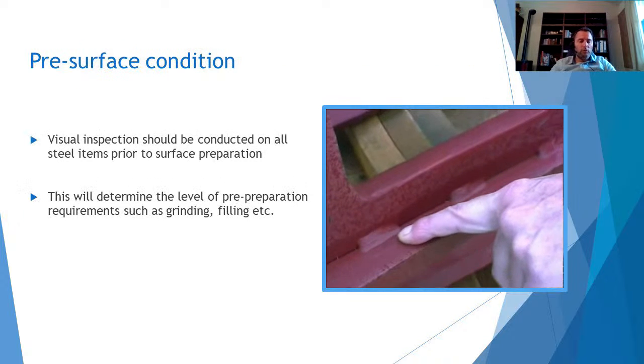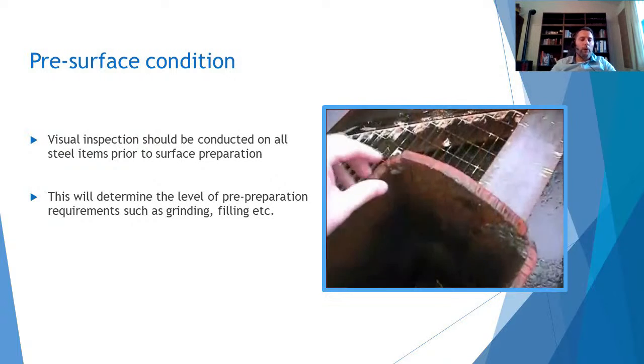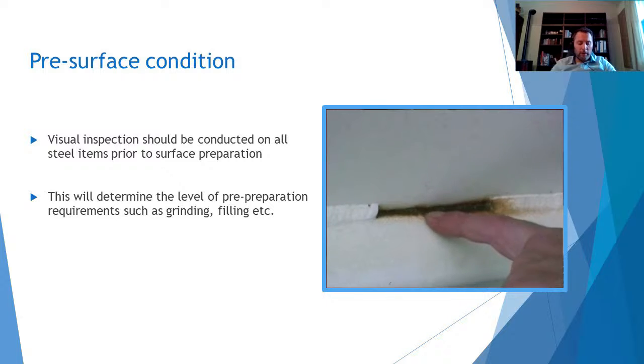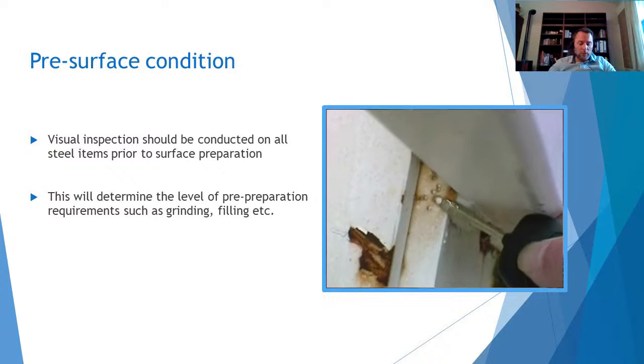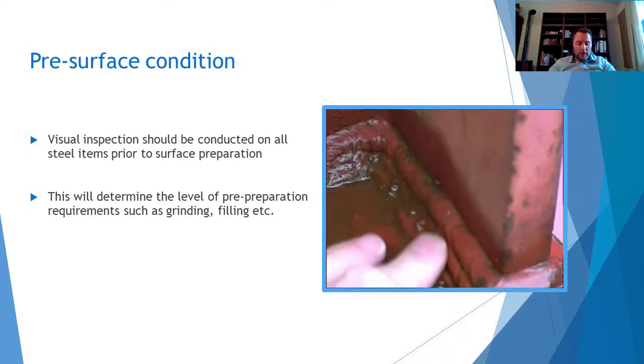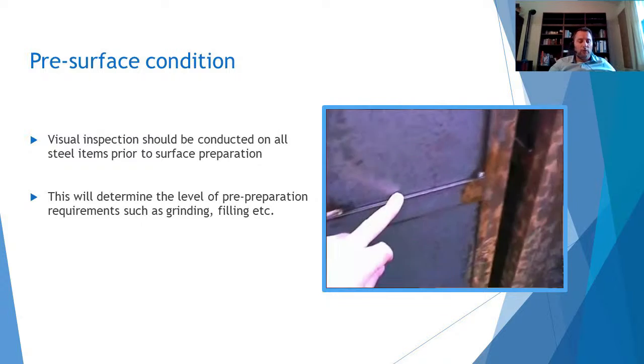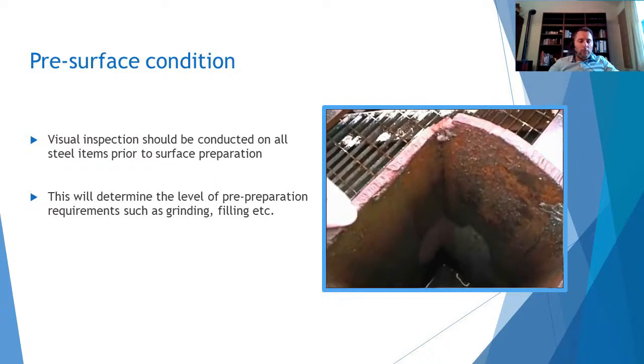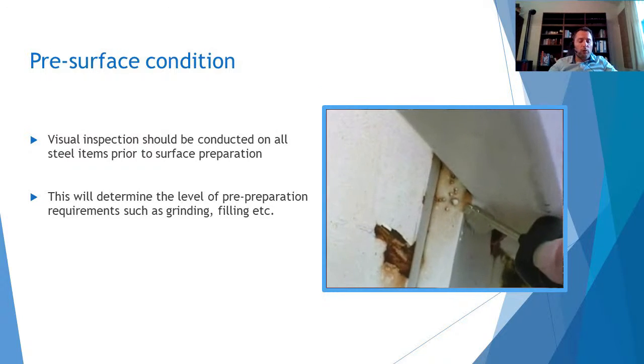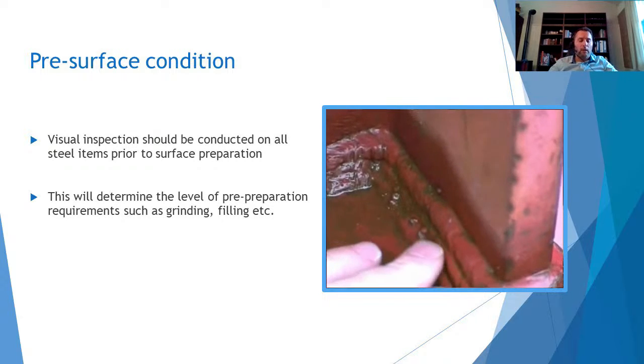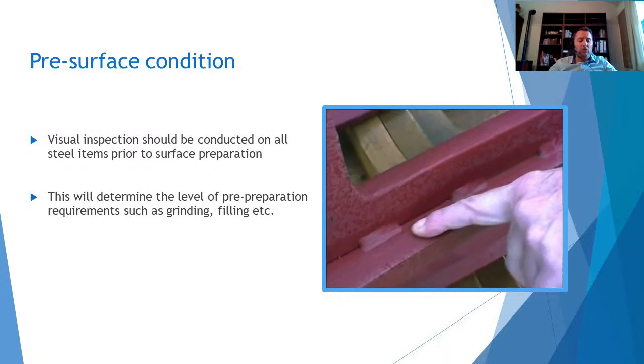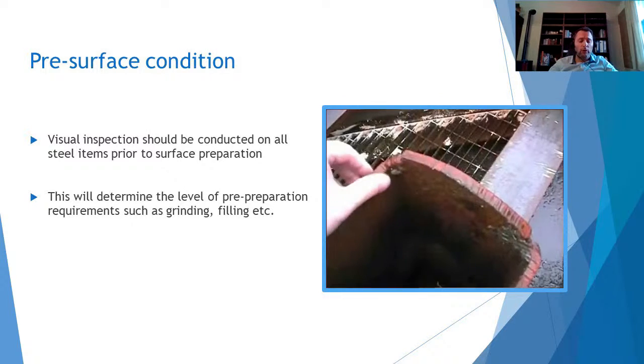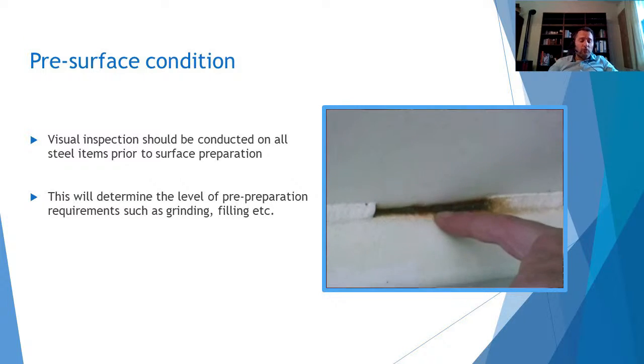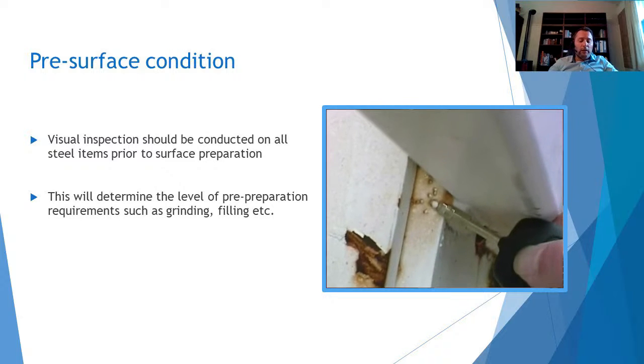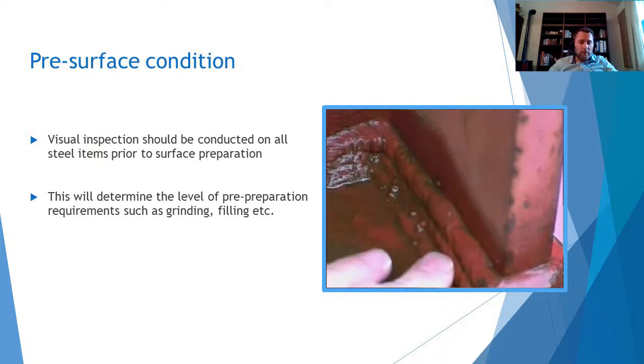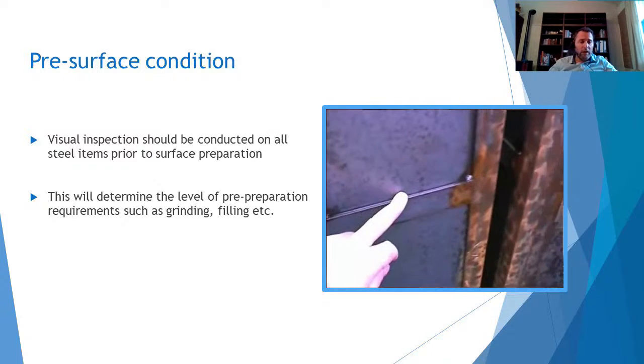Pre-surface condition: visual inspection should be conducted on all steel items prior to surface preparation. Many factors in surface preparation affect the life of a coating, including residues of oil and grease, which can prevent adhesion or mechanical bonding of the coating to the substrate. Other potential problems related to the condition of the surface are residues of non-visible chemical salts that can induce corrosion after the coating. Rust on the surface is another problem. Another could be mill scale, both loose or tight, which can cause early or later coating failure. Another problem is related to sharp ridges, burred edges, or cuts from mechanical cleaning equipment, which can prevent adequate DFT. This will determine the level of the preparation requirements, such as grinding and filling.